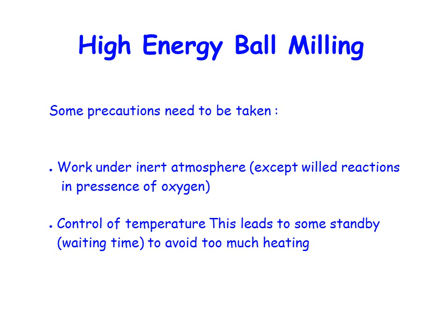And the other thing is that the work done by the ball mills is going to transform into heat, and so the temperature can increase and modify the evolution of the microstructure or nanostructure, and also the crystalline structure of the material. So if temperature plays an important role, then you need to stop the milling from time to time and start again, just to let the sample cool down.